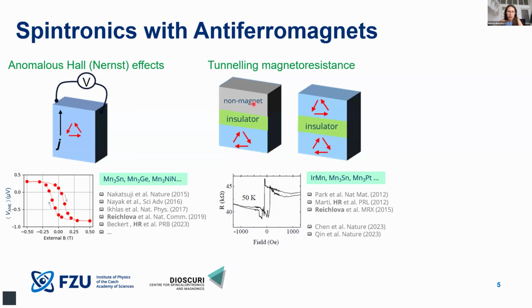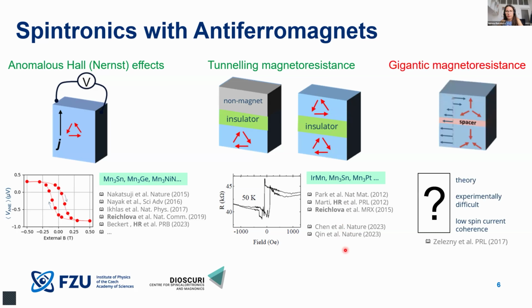The difficult part in this particular case is that, as I said, the signal is very small, and there is not much space for improvement of the signal. And also that one has to find some sweet spot where this electrode can be partially reversed to get some sort of anisotropic signal. So this was the status a couple of years ago, and last year or 2 years ago, there were two, I think, very important papers which showed that in two antiferromagnetic electrodes separated by an insulating barrier, one can indeed measure full antiferromagnetic tunneling magnetoresistance, by these two groups, which again, I think, is a very big step for antiferromagnetic spintronics. And the last thing which I want to mention,